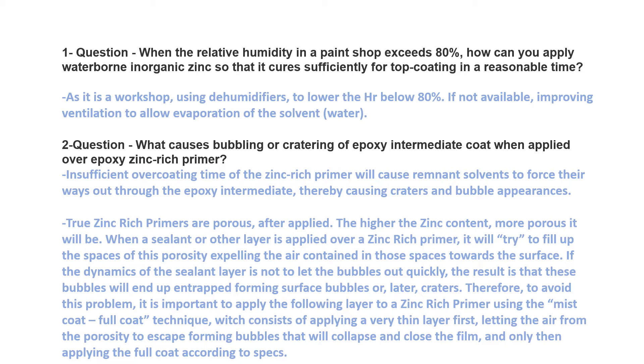There are two answers for this question. The first one is: if insufficient overcoating time is given for the zinc rich primer, then remnant solvents will be forced to push their way out through the epoxy intermediate coat. That would be the cause for bubbling and cratering.